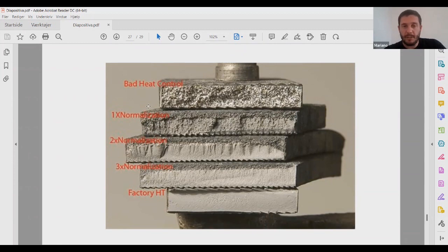So when we finish all the forging process, we are going to do the normalization process. We heat to the critical point. This depends on the steel, and we heat three times and let it cool as slowly as we can, and then we are going to temper. To temper this knife, I'm going to use oil because it's the correct cooling method for this steel. And we are going to put it in this way, like an angle, and only to this place. We are going to keep soft all the bolster area and this area also. So we are going to harden all this part of the knife.